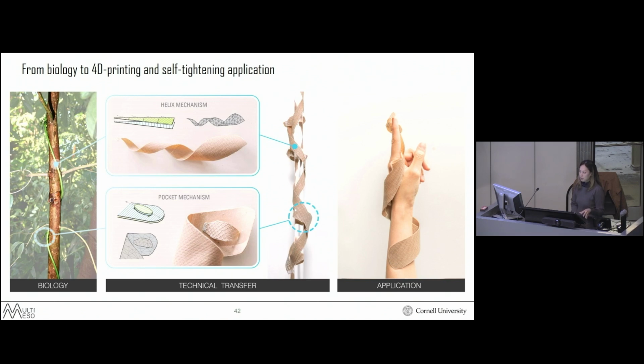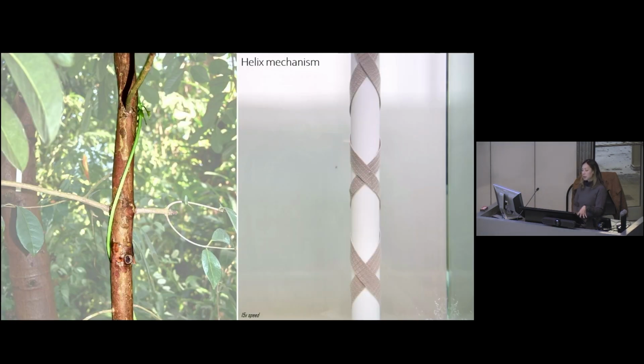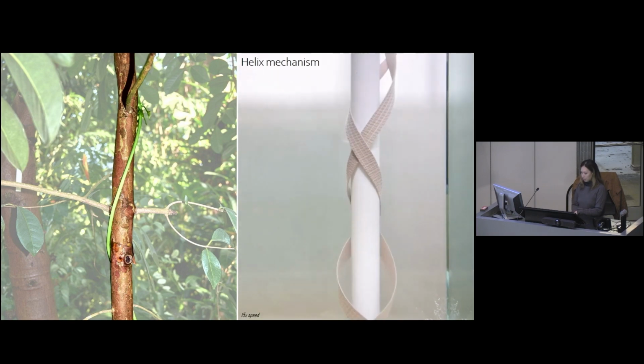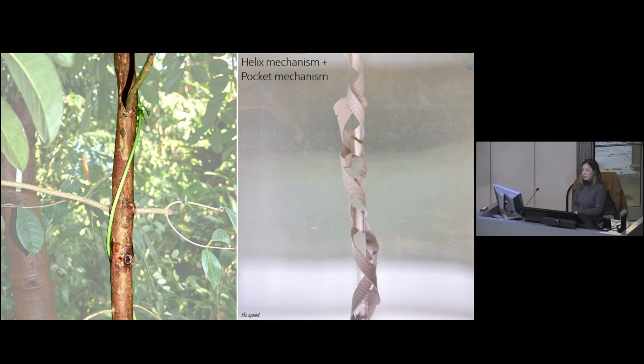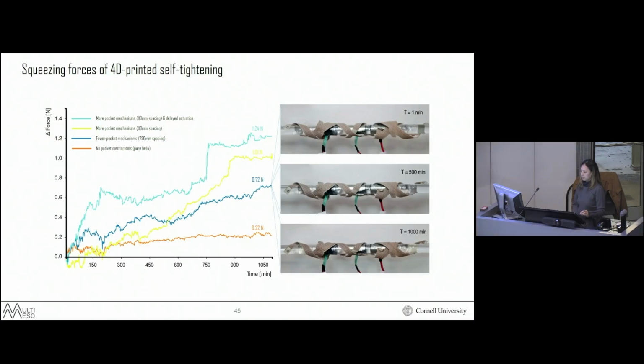So we first tested the 4D printed material system's ability to stay gripping onto a support pole. And here you can see the pure helix mechanism gripping onto a 30 millimeter diameter pole and self-releasing after 40 minutes of moisture uptake. And in comparison, the same helical system, but with pocket mechanisms, was able to adapt the grip for thicker 50 millimeter diameter poles and also stay gripping for well over 3 hours during moisture uptake. And the key was understanding the mechanism that the air potato plant uses in order to generate that force.